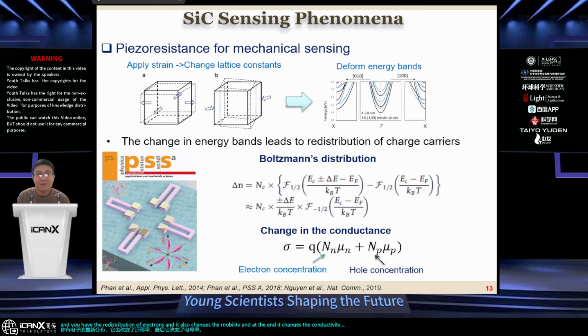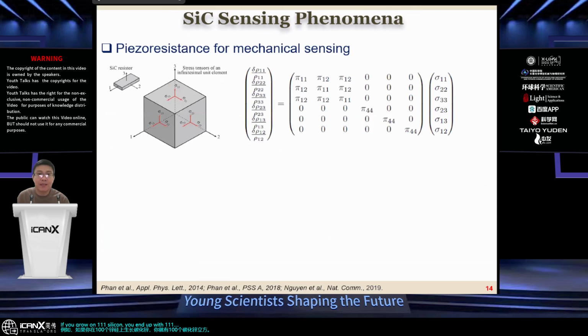And because we grow silicon carbide on silicon, we expect the material to have similar crystal orientation. For instance, if you grow silicon carbide on 100 silicon, you have 100 cubic silicon carbide. If you grow on 111 silicon, you end up with 111 cubic silicon carbide. And we know that the piezoresistive effect in silicon is orientation dependent, so we expect the same phenomenon in silicon carbide. And we build this kind of piezoresistive coefficient tensor to investigate the orientation dependence of silicon carbide for mechanical sensing.